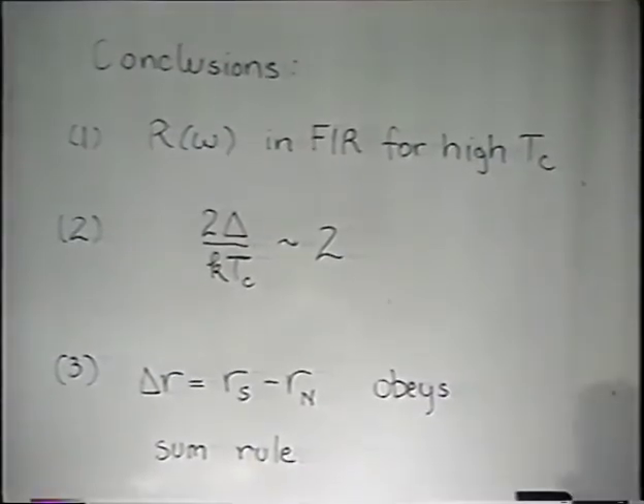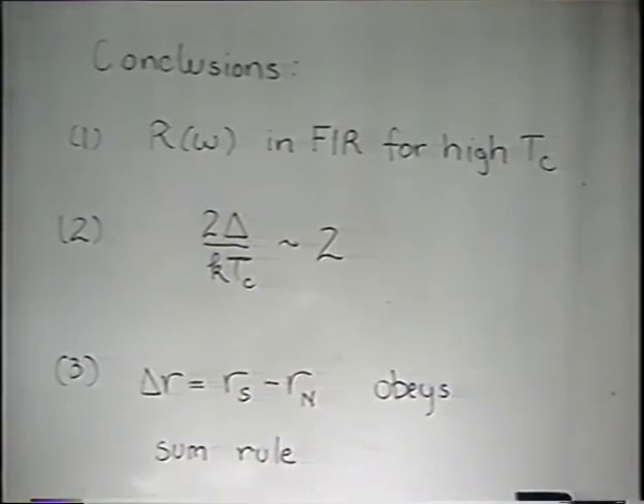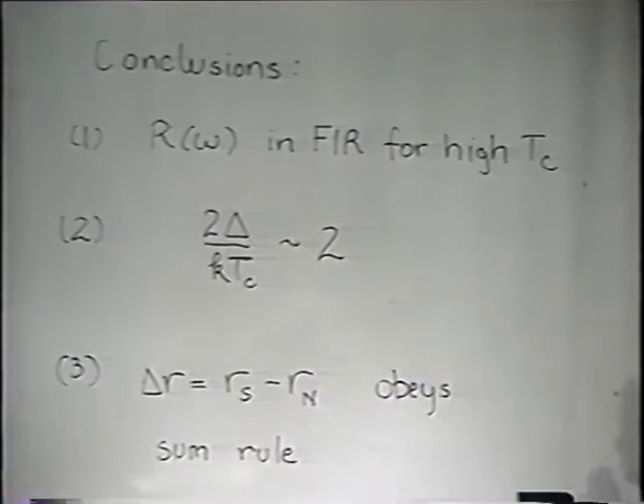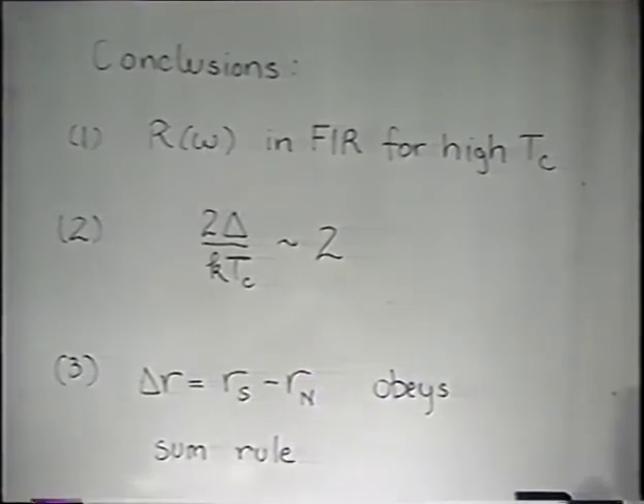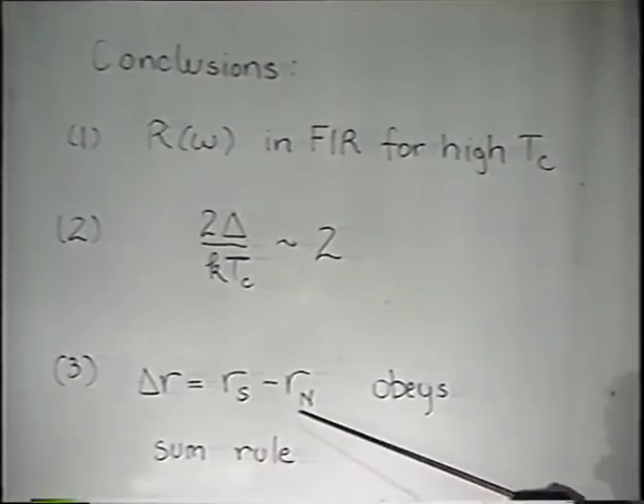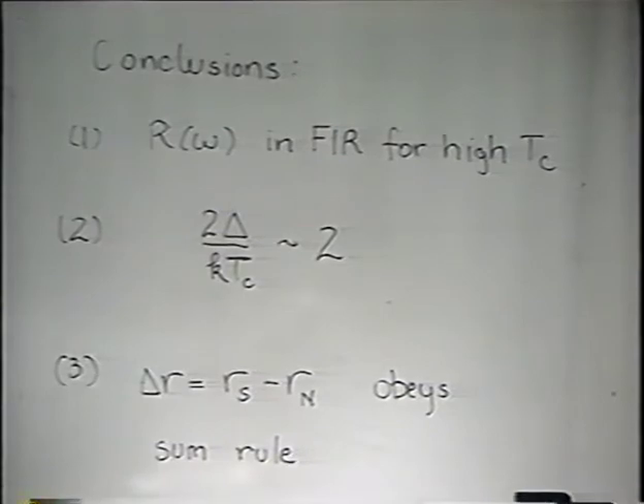So I think we'd like to stress in conclusion that we've measured the frequency-dependent reflectivity in the far infrared for these high-temperature superconductors, and that systematically, no matter which one we look at, we see 2 delta over KTC is much smaller than BCS. About 2 would be a good round number. And we see that the difference in the surface resistance obeys the sum rule. Thank you.